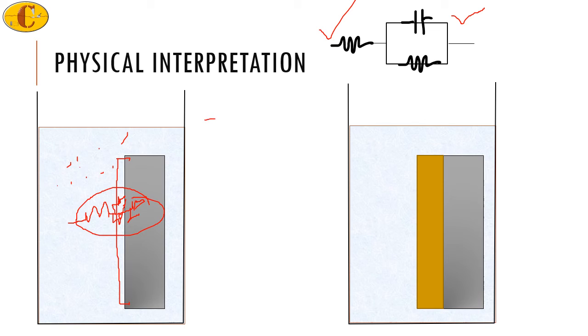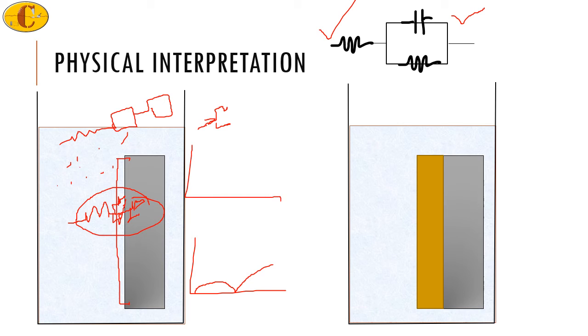So in this case, you may want to consider two parallel arrangements. So you'll have a resistor, then you have a parallel arrangement, and you have another parallel arrangement. So in this case, the typical plots that you get would be two semicircles or two arcs. If your inhibitor film is very good, then in that case you may not see the second arc. You may only see a single arc, because there the metal is not going to play any part in corrosion, as the inhibitor is completely protecting it from the corrosive medium. So we can eliminate the second parallel arrangement and only consider one RC circuit.